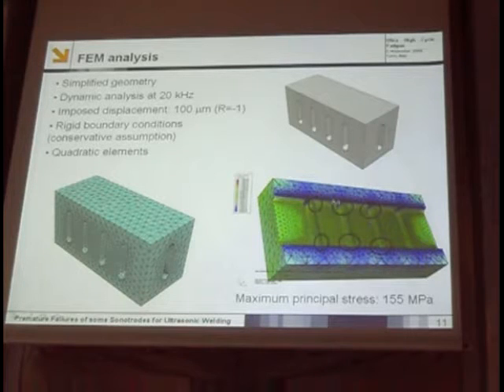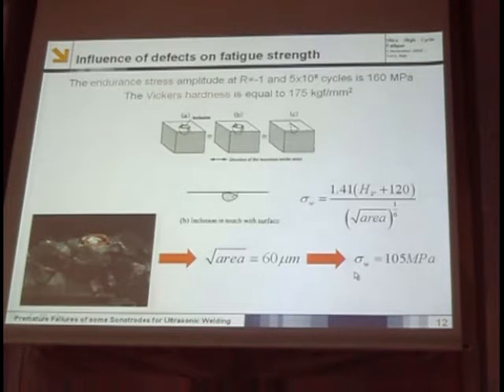We used quadratic elements, and we found the maximum stress exactly where we found the cracks. So here at the stress concentration in this position and in this position. The value of the maximum principal stress was about 155 megapascals. So I decided to make a comparison between these 155 megapascals with the fatigue endurance limit, not the fatigue limit, because we know that there is no fatigue limit for aluminum alloys, but the endurance limit of the Ergal alloy. We are not sure that the material here was really Ergal alloy, but we don't know what it really is. So actually, we use this one.